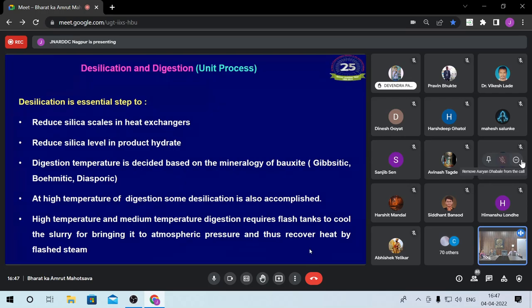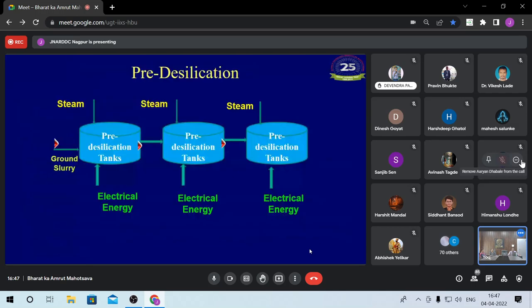For 240 degrees, to bring it down to atmospheric pressure, you require around 7 to 8 flashing tanks. For 145 degrees, you require 2 to 3 flashing tanks. And whatever flash steam you are getting has a lot of enthalpy, and that is used back in the process for heating the cold slurry. So there is a heat exchange process taking place, which is of very much importance to chemical engineers.